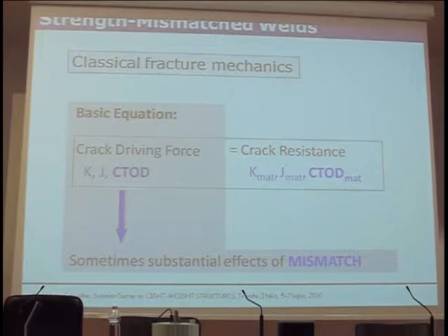Okay, and we should always keep in mind that failure conditions, stability conditions, are given by an equation. On the left-hand side, we have the driving force, on the right-hand side, we have the material's resistance. This is absolutely parallel to what we do in classical strength calculus, where on the left-hand side we have a stress, however determined, and on the right-hand side the material's resistance. So in principle, it's nothing new. Fracture mechanics can be regarded as a method for strength calculus, but in this instance, we have a crack.